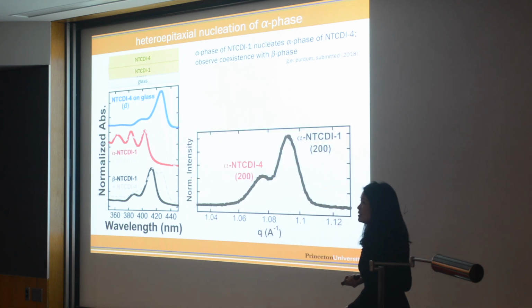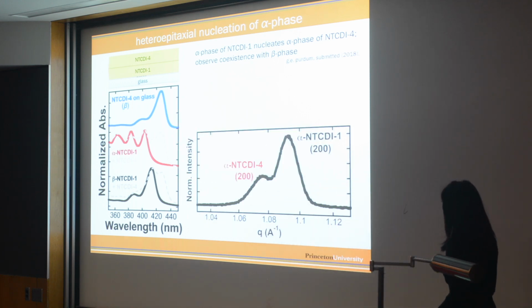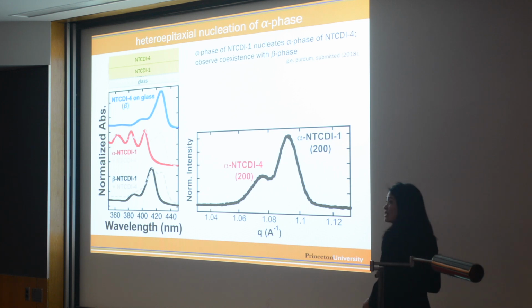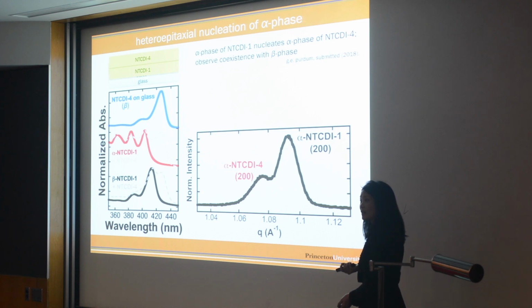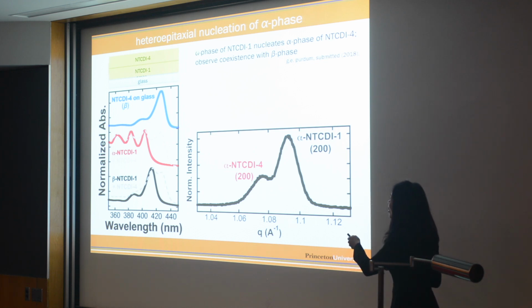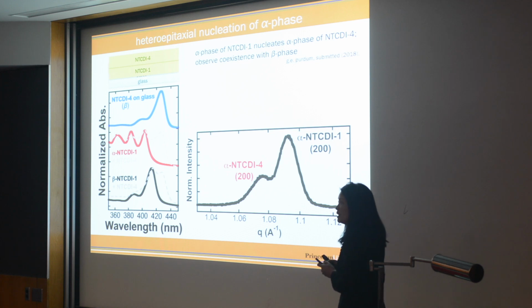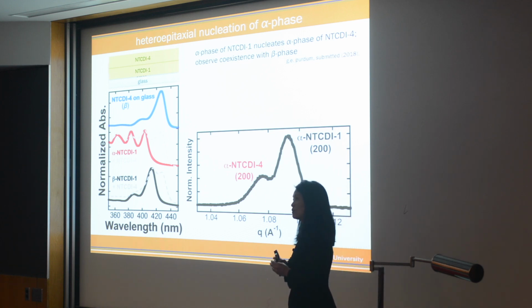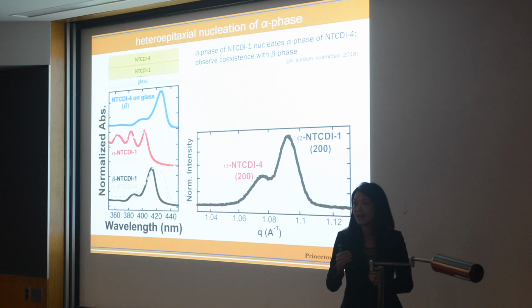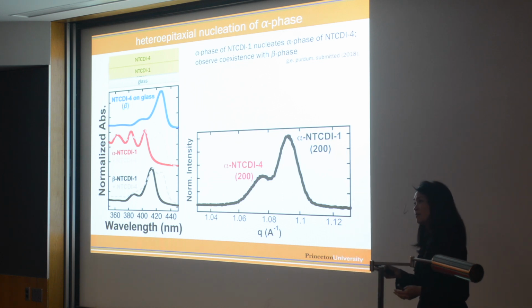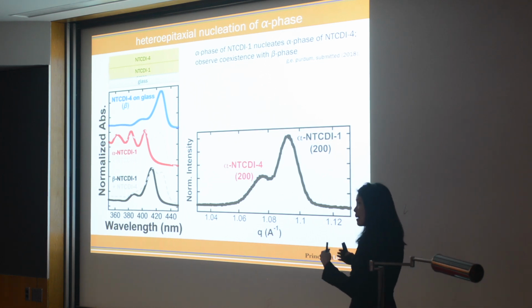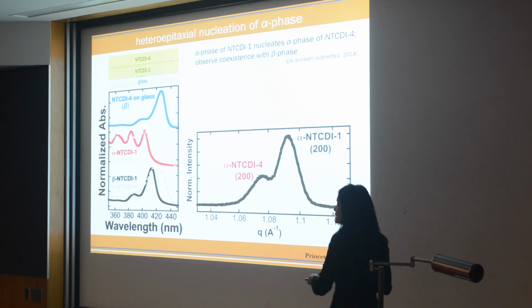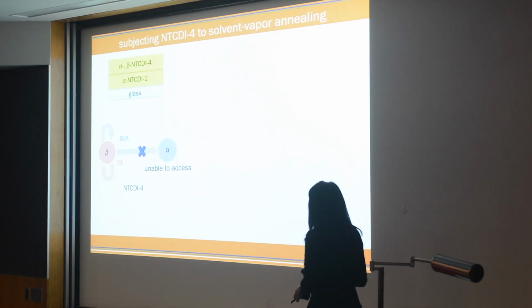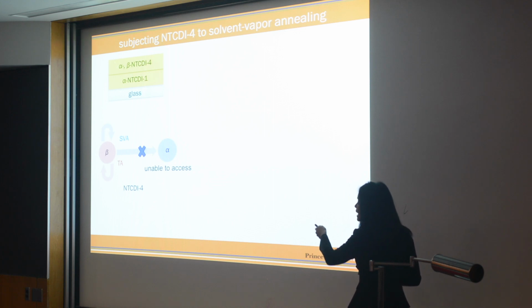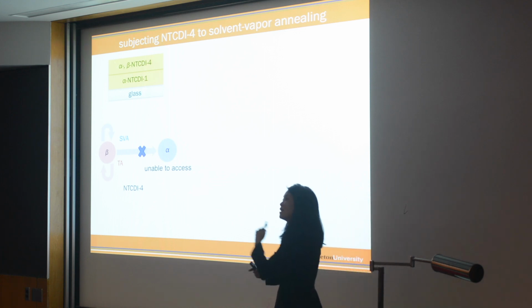If you don't believe me, you can also look at the X-ray diffraction data, and this is more concrete, I would say, because you see a separate reflection that's associated with the alpha phase of NTCDI4. Now, I should mention that we don't get all alpha phase of NTCDI4. We get a fraction that's alpha phase. We still have a fraction that's beta. And that fraction depends on the thickness of the film, a telltale sign that this is a heteroepitaxial templating of NTCDI4.